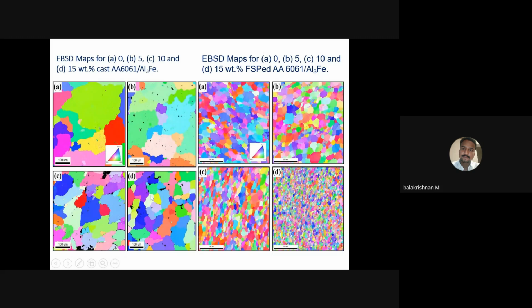Similarly for 15%, even though there is agglomeration and dispersion of particles, the sharp particle morphology and pores are not desirable for enhancement of tensile strength, as we know. So the microstructure needs to be refined using some other deforming techniques.